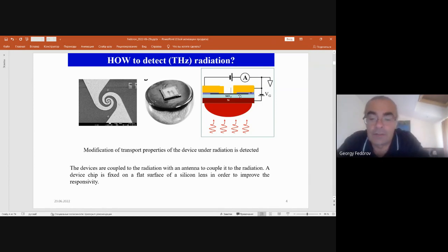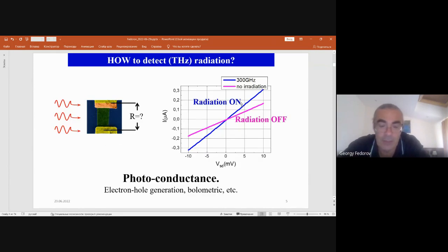conductivity of the object you have. Just simply applying some voltage, you measure the current, and you also have an opportunity to apply a gate. In this case, you use the silicon wafer as a back gate electrode. Okay, so the response you can measure comes in two varieties. First, you can detect photoconductance. Like here I show two IV curves of whatever it is, and they have different slope. The IV curves are measured with and without radiation. And this is what's called photoconductance.